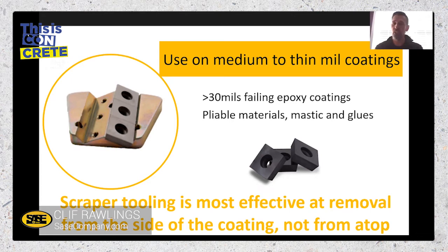RPMs, we typically say start on the medium to lower side of things. As far as the SASE grinders, we have a potentiometer speed dial that goes from 0 to 10. And we typically start on coating removal somewhere around a speed 4, which is a good starting point. And I always say, try it, push the limit, see how far you can go with it and still be productive. So go ahead and crank it up a little bit, and increase your walking pace when you increase your RPMs,